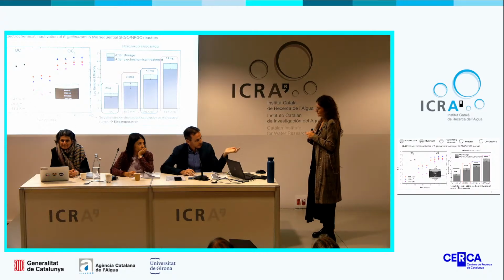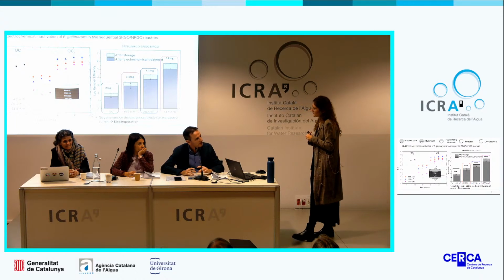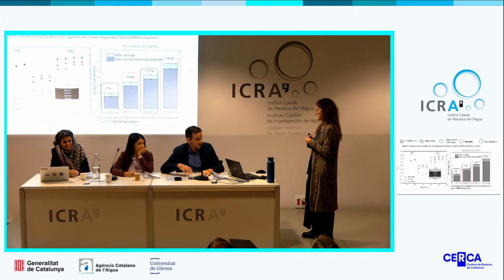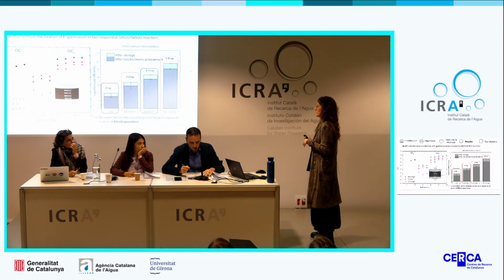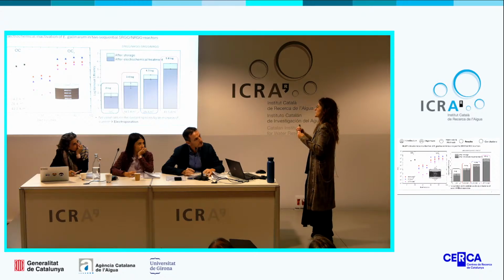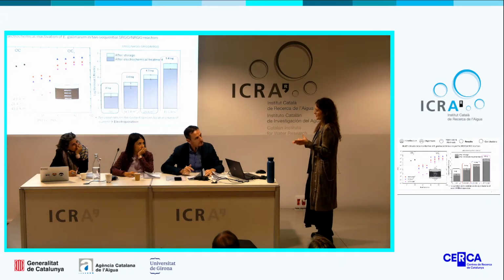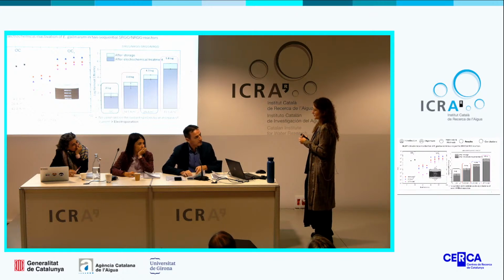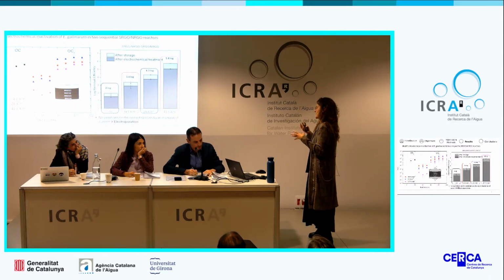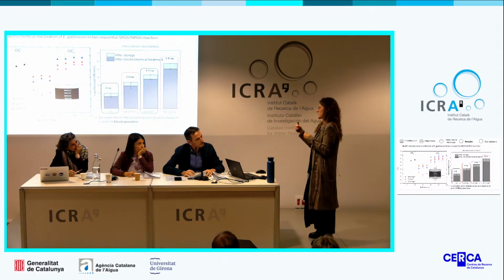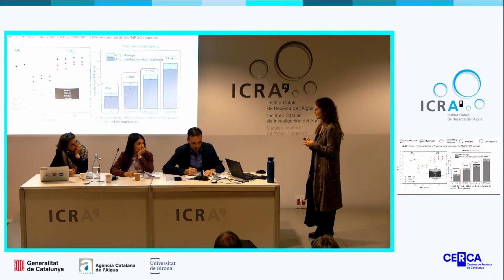Why use reduced graphene oxide modified with these elements instead of graphene oxide? Sorry? Which is the advantage of using reduced graphene oxide modified with these elements instead of using the same elements modifying graphene oxide? Which is the interest of reducing? In comparison with graphene oxide. Okay, so graphene oxide is an insulator, and reduced graphene oxide improves the conductivity. And it still preserves some oxygen groups, which are important for the different interaction with the contaminants, but especially because it's a more conductive material. Okay.